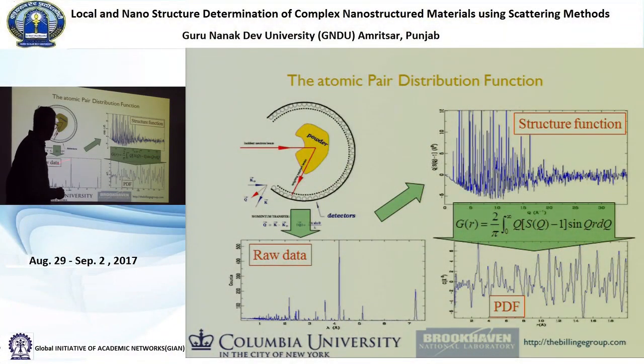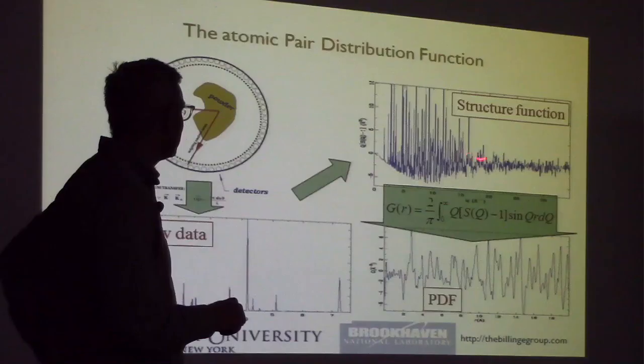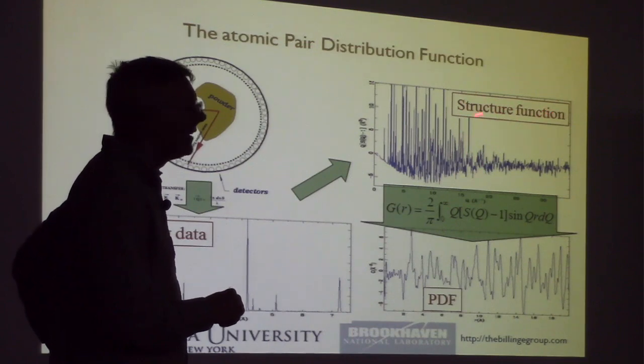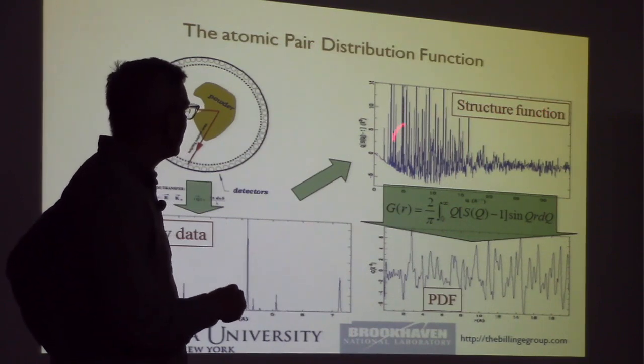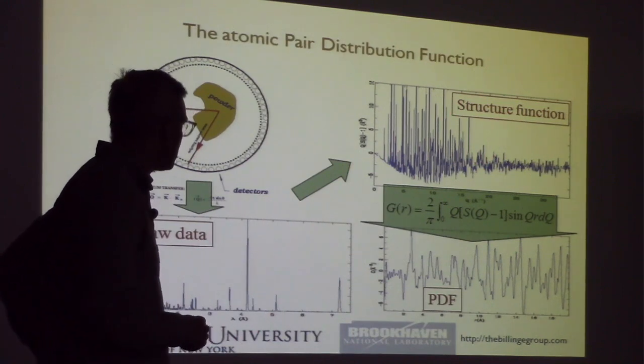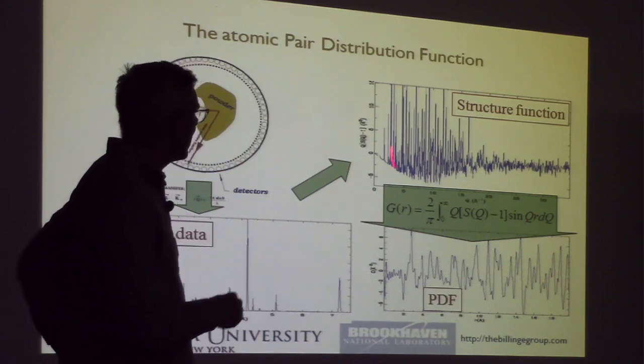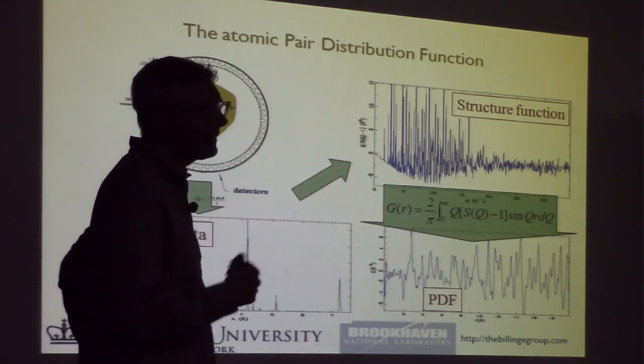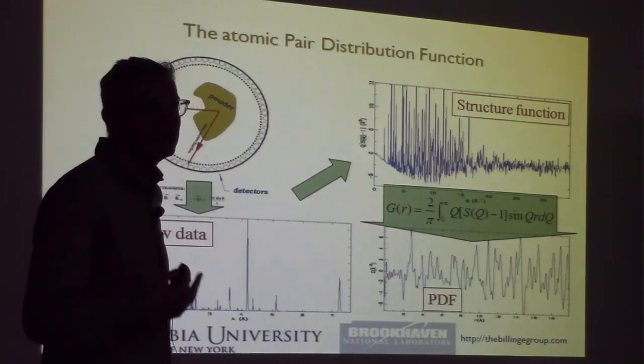So what we do is we do data corrections to get from the raw data to a function that we call S of Q, the structure function. So this is the structure-dependent part of this measurement. And there's two very special things about how we measure this structure function. This is like a powder diffraction pattern that you measure in the lab, and probably many of you have actually measured powder diffraction patterns. That's all this is.